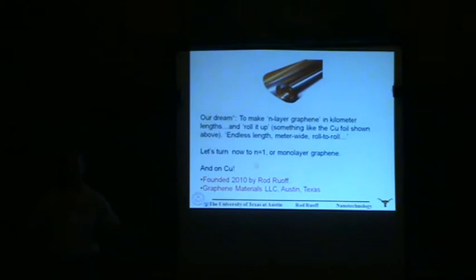So suppose we are sitting around thinking about how to grow graphene on a metal, and we want to use a metal foil, because metal foils are available in very large areas, such as copper or other choices. Well, typical thicknesses of metal foils, just so that they would be stable, are sort of tens of microns in thickness. If I use a nickel foil, tens of microns in thickness, so much carbon might dissolve into the nickel that I would get graphite on the surface. And in fact, we've done that. But our thinking was if we took copper, then at least the solubility is projected to be so low that maybe a standard copper foil, 100 microns in thickness, might give us graphene when we cool down.